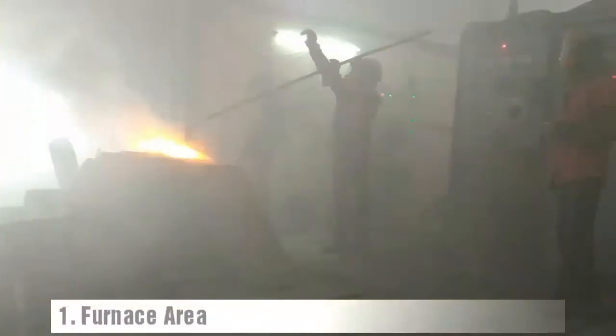The formation of nickel aluminum alloy in a certain ratio takes place in this furnace. As working of this induction furnace is based on the concept of eddy currents, the temperature of 1400 degrees centigrade is achieved by 70 volts only.